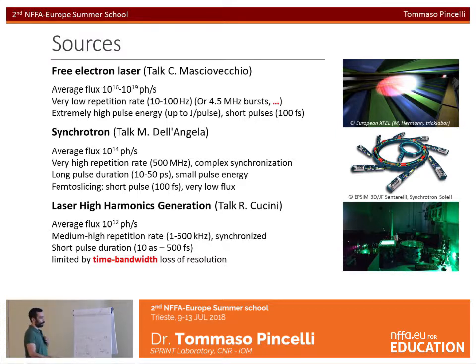And then you can have very short pulse duration. Obviously, in choosing the pulse duration, you can tune it quite easily in high harmonics. You have to keep in mind the time-bandwidth limit. So if you squeeze the pulse too short, then you will need a broader spectrum of the pulse, and vice versa. So we settled in our laboratory to around 300 femtoseconds, so as to generate very high resolution for photoelectron spectroscopy, which is needed.